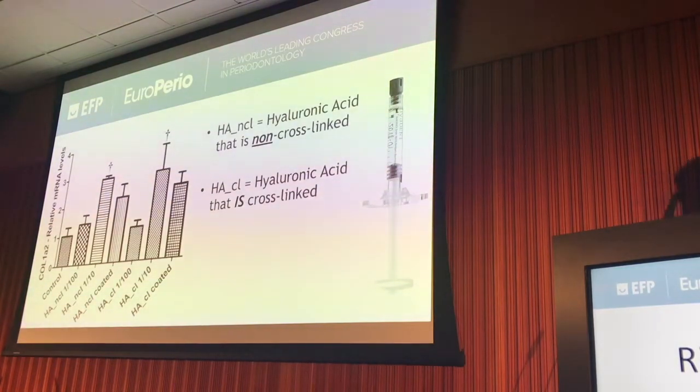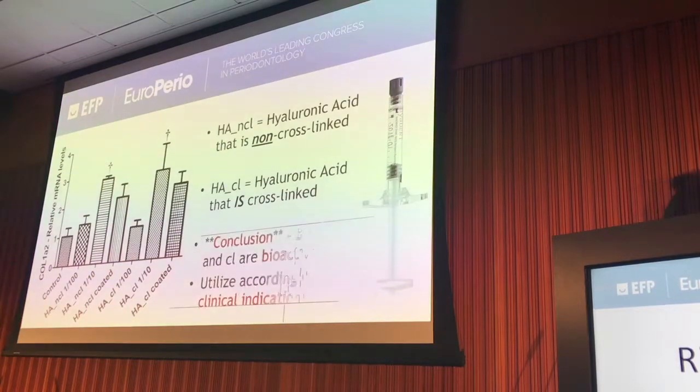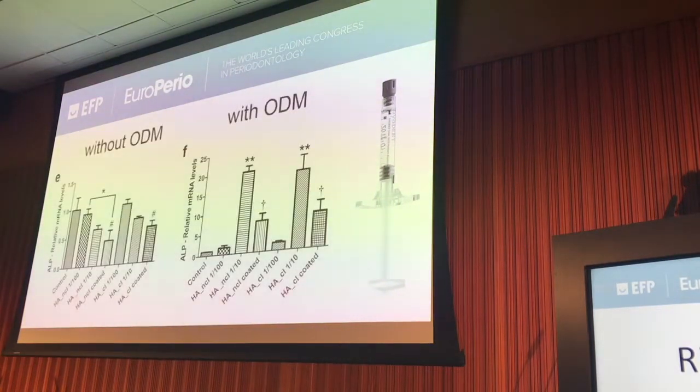It doesn't matter if it's cross-linked or not, it's still bioactive, okay? So when I talk about the molecule being cross-linked, it's going to help you later on in clinics, and I'll explain why. The degradation properties of cross-linked hyaluronic acid are much, much longer. So when it's cross-linked, basically the hyaluronic acid, which I consider a bioactive agent, lasts longer and is not degraded very, very fast. But it's not to say that if you use hyaluronic acid in a liquid formulation, it's not still very bioactive, right? Exactly the same. Okay, so conclusions here: both are bioactive, and then you can utilize them according to the clinical indications here. I'm sure the clinicians will talk more about that.